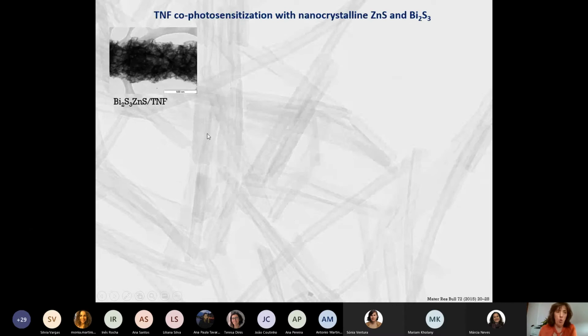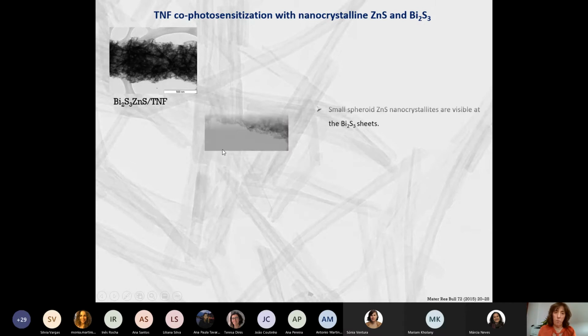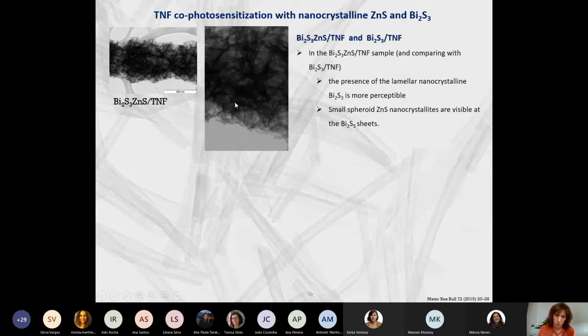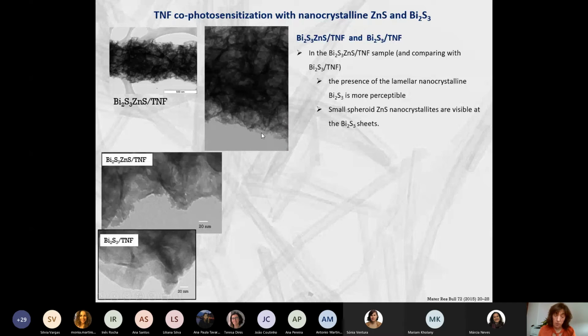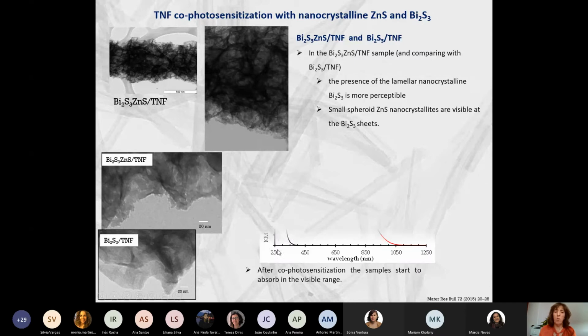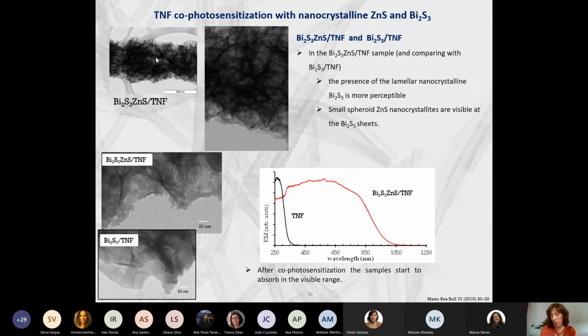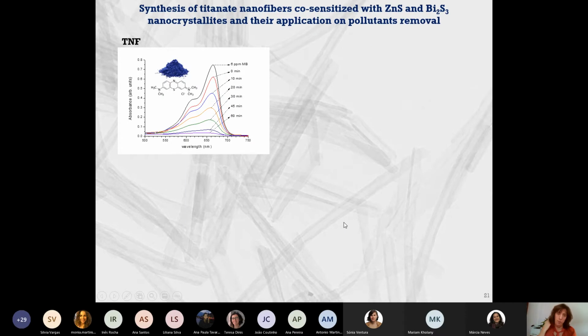But I would like to show you this material, which is the combination of bismuth sulfide and zinc sulfide nanoparticles on the surface of titanate nanofibers. We have prepared this. This is the bismuth sulfide and the crystallites of zinc sulfide. As you can see here, it's easier to see the sheets of bismuth sulfide and some small dots that are the zinc sulfide. Of course, we know that if we are using bismuth sulfide, we will have an increase in the absorption of this material, but I would like to show you a different